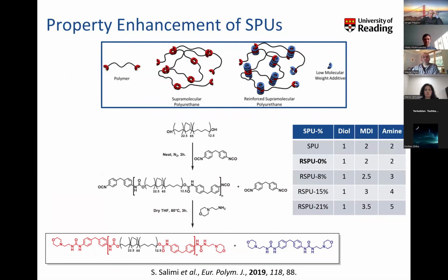Now, I'll just finish off by showing you that actually making pure materials, as we've spent 20 years trying to do, isn't always the best way to produce materials with the best properties. So what we've typically done is we've taken our polymeric diols, reacted them with the diisocyanates, and then end capped them, and then precipitated and purified our polymer, knowing full well that we're removing a low molecular weight bisurea if we use amines, or bisurethane if we use diols as a nucleophile.